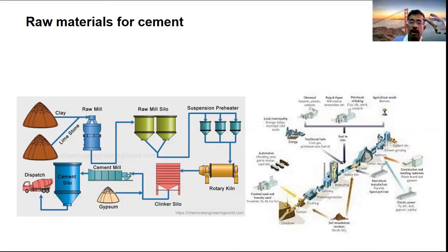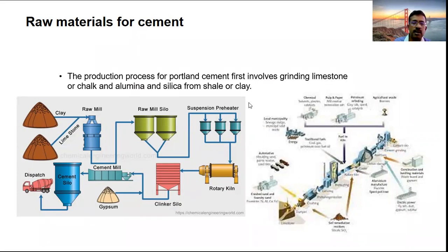This is the manufacturing process of cement. We get all the raw material, clay and limestone, and it comes to the raw mill. From the raw mill to a raw mix silo. Then it goes to the preheaters. Then we get the clinker from the rotary kiln. Then the clinker will be stored in a silo, and in the ball mill, we grind the clinker along with gypsum, or we grind it using fly ash or slag to get various types of cement: PPC, OPC, slag cement. And finally, it gets dispatched to the customers.